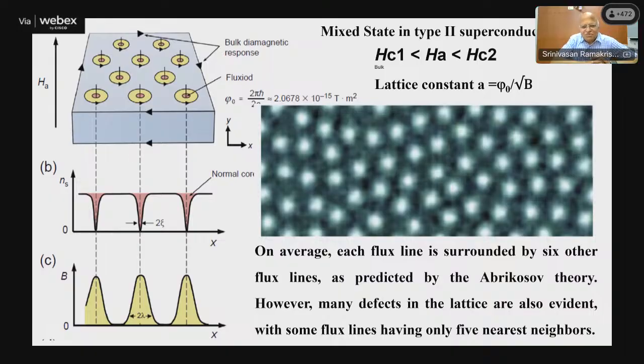We thought that because it cannot have an inhomogeneous magnetic field distribution, the magnetic field penetrates in terms of vortices. And these vortices you can observe by experiment. This is a Bitter experiment where you spread fine magnetic particles, and the magnetic particles go to this normal region, and you can form a triangular lattice. Now, of course, we have optical techniques where you can neatly picture this triangular lattice.